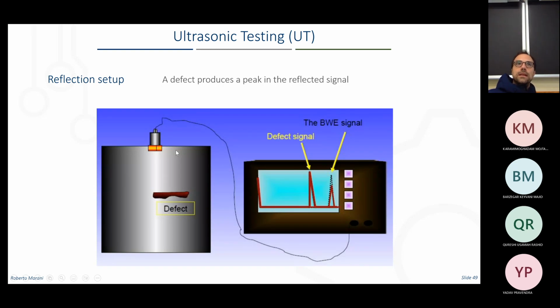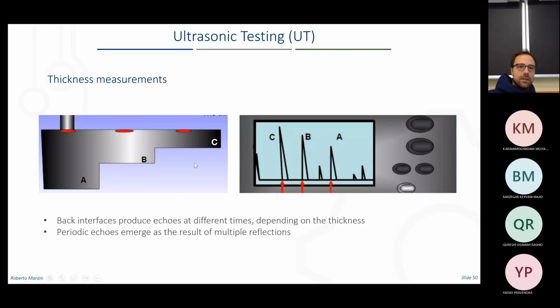So there's a resonance. This means that once you look at your amplitude in time, like here, you will see, for example, with thickness of this point C, you will see the first peak, and then there's another peak, this one, due to the resonance, and there's a third peak here due to the resonance. The peak B produces a peak here, and then another peak, for example, here. So there's a periodicity, of course, due to the resonance of the wave that is flowing through the material, goes back, and then again to the defect or to the discontinuity, to whatever you have within your material.